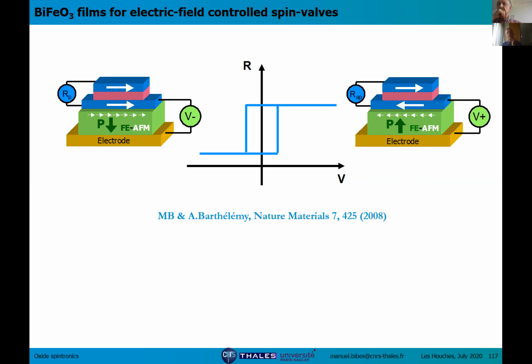Okay, so if you use, for instance, gold instead of iron, then in terms of spin-dependent tunneling, I guess you will not see any TMR, but you may see, for instance, TAMR. That's another effect called tunneling anisotropic magnetic resistance. But as regards the tunnel electroresistance, I think it will be the same. The tunnel electroresistance does not need the materials to be ferromagnetic.